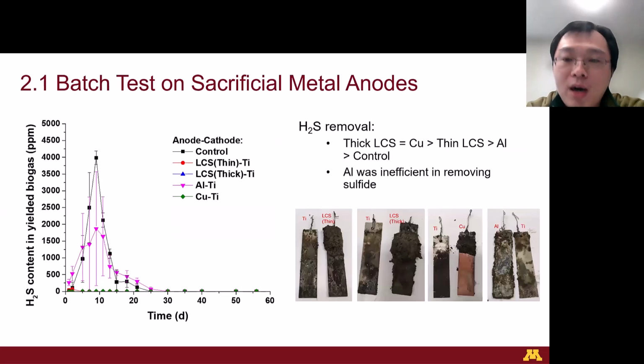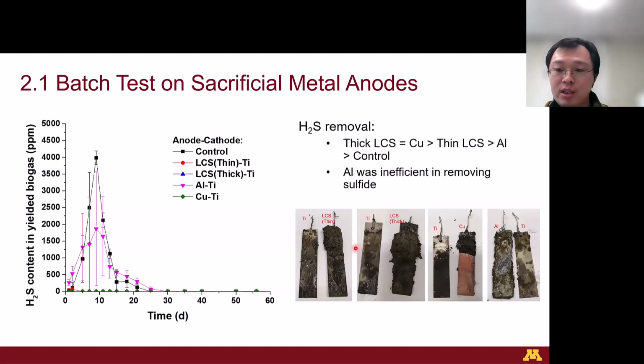So in this experiment, we tested several different sacrificial metal anodes, including low carbon steel, LCS, aluminum, AL, and copper, Cu, against a durable titanium cathode, Ti. All results showed that low carbon steel and copper had the highest hydrogen sulfide removal efficiency, while aluminum actually was not effective in removing the sulfide from manure. We can also observe different precipitates or attachments on the electrode surface after the experiment.